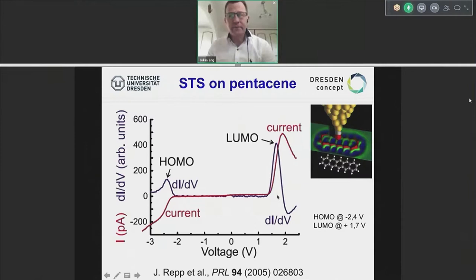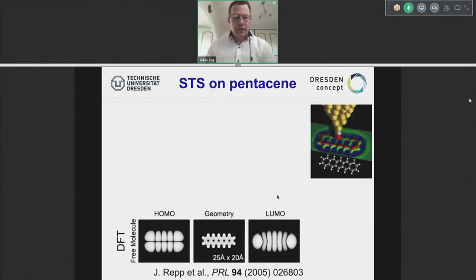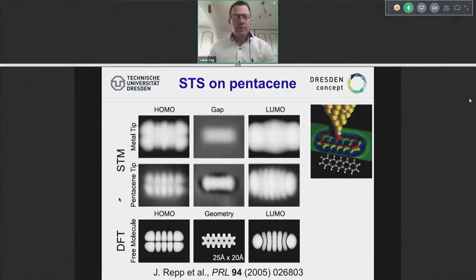So, fantastic work, which led them to do some more work. In fact, they said, okay, why can't we write a textbook chapter by looking at the HOMO-LUMO of this kind of pentacene molecule, by looking at the chemistry of this system. And that's exactly what they did. They said, okay, let's do a comparison DFT calculation, and then do the measurement, and you see the measurement done by STM with two different tips, but both of them show exactly the same quasi-HOMO behavior, depending on whether you cover your tip with a pentacene molecule or you take your tungsten tip barely as it is. So this is really textbook quantum mechanics. The best thing I would say that you can use for your students when they want to learn something about these fundamental HOMO-LUMO things.